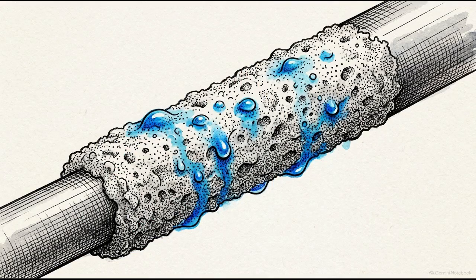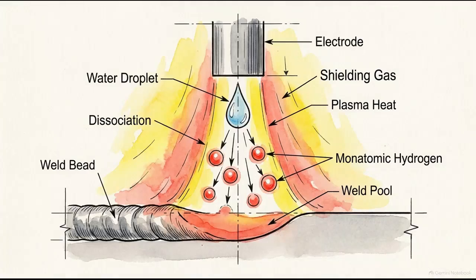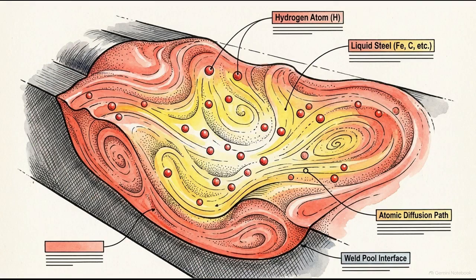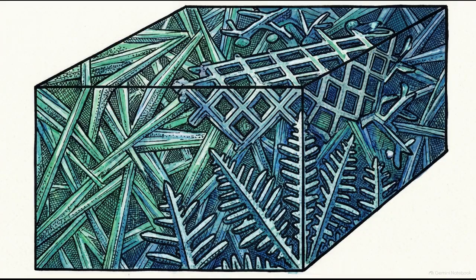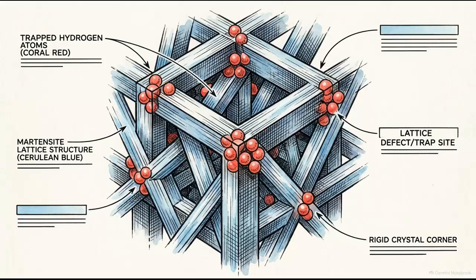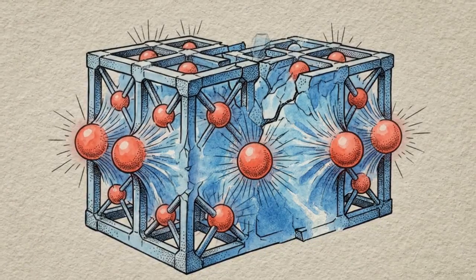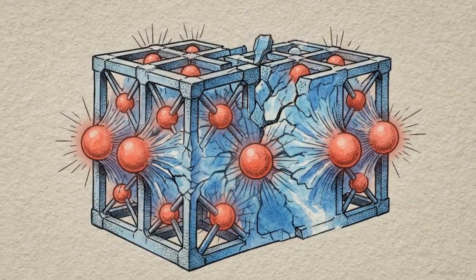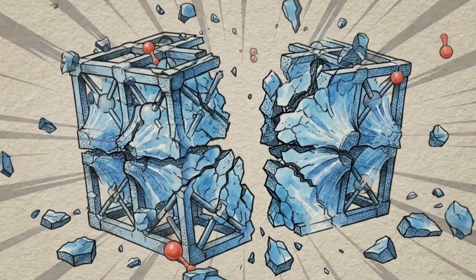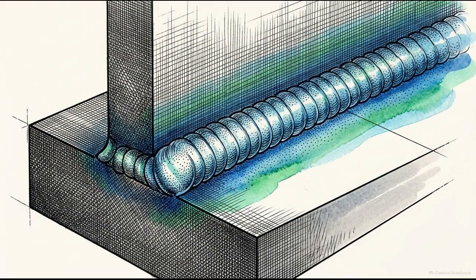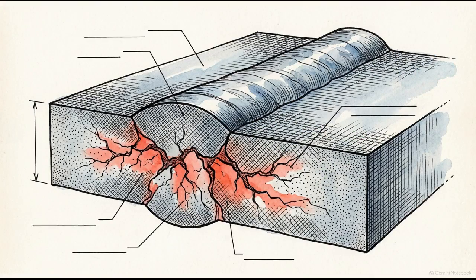An even more dangerous chemical threat occurs if a E7018 rod absorbs ambient moisture from the air. The extreme heat of the arc breaks that water down, releasing monatomic hydrogen directly into the plasma. This hydrogen readily diffuses into the liquid metal. If the weld cools too rapidly, the steel transforms into a hard, brittle microstructure called martensite, permanently trapping those wandering hydrogen atoms inside the rigid crystal lattice. Internal pressure builds until the tensile limit is breached, and the steel violently tears itself apart from the inside. This is hydrogen-induced cracking. A weld can look visually flawless on the surface, while hiding fatal atomic-level fractures caused by a mismanaged thermal cycle or contaminated flux.